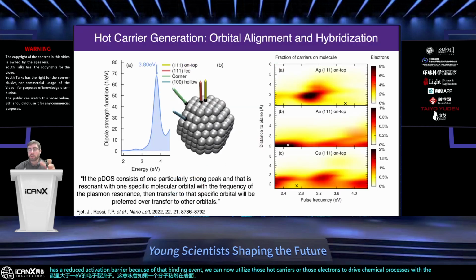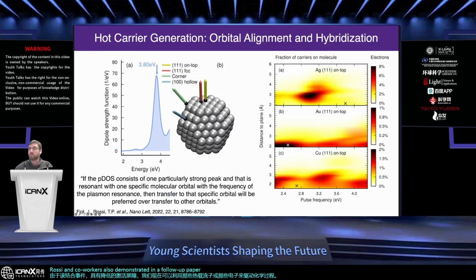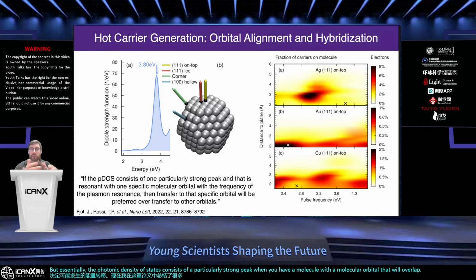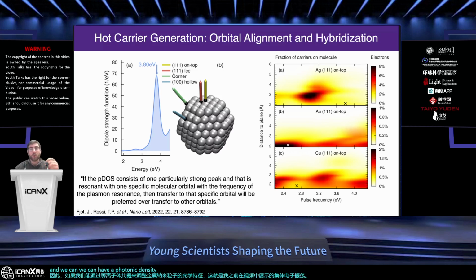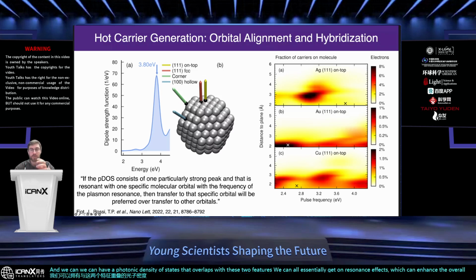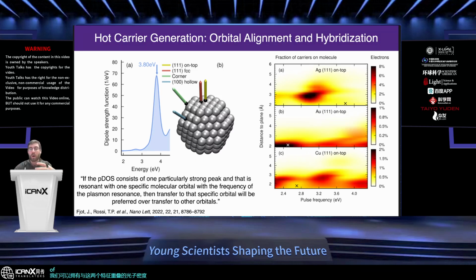Rossi and coworkers also demonstrated in a follow-up paper published in Nano Letters in 2022 that the location of, let's say, a binding molecule is going to dictate the energy transfer that can take place. Now, I'm summarizing a lot in this paper here, but essentially, the photonic density of states consists of a particularly strong peak when you have a molecule with a molecular orbital that will overlap with the frequency of a plasmon resonance. So if we can tune the optical features of a metal nanoparticle by a plasmon resonance, that's the collective electronic oscillation that I showed a video of before, and we can have a photonic density of states that overlaps with these two features, we can essentially get on-resonance effects, which can enhance the overall energy exchange of the electrons, the hot electrons I was telling you about before, into molecules of interest.